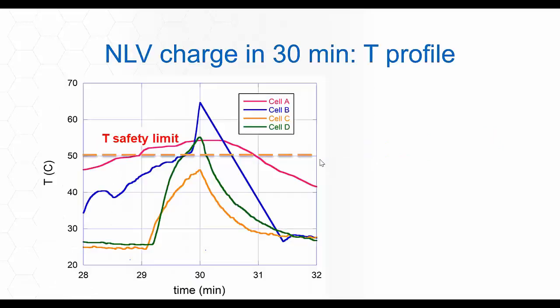Okay, so this stress test, basically what we do is we charge a battery, for instance, in 30 minutes, and we look at the temperature profile during the charging in 30 minutes. And if we put the limits of safety at 50 degrees C, so we have here 4 cells, A, B, C, D, and you can see that for cells A, B, and D, all these 3 cells, the temperature exceeded 50 degrees C, okay? Only one battery, which is cell C here, had the temperature below 50 degrees C. So for that charging in 30 minutes, only cell C passed the test, okay? Very important. So I will not use cell A, cell B, and cell D to charge in 30 minutes using NLV. Otherwise, there is a risk of thermal runaway, okay?